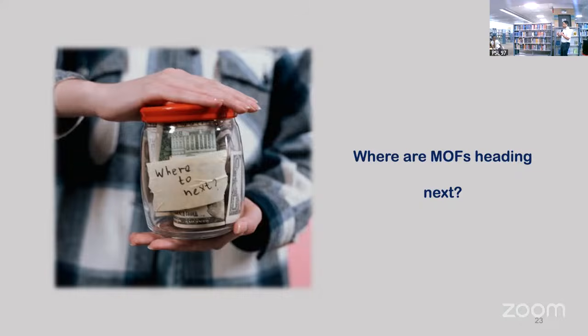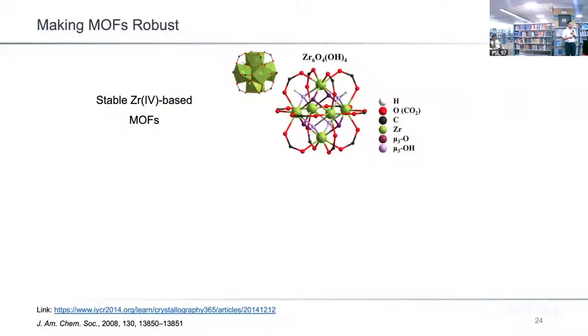Before I actually show some of these applications, I wanted to highlight two more examples where this field has actually exponentially grown. So the first example actually came in 2008 from a group in Norway. And what they did essentially, until that point, all the MOF structures that were known, even if they were robust structures, they were very moisture sensitive. So the moment you put the structure in high humidity, let's say put it in Chennai weather, they would start collapsing because the water molecules bind well to the metal ions, disrupt the structure, and collapse it.